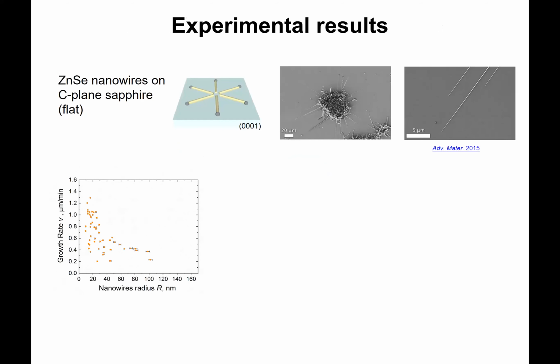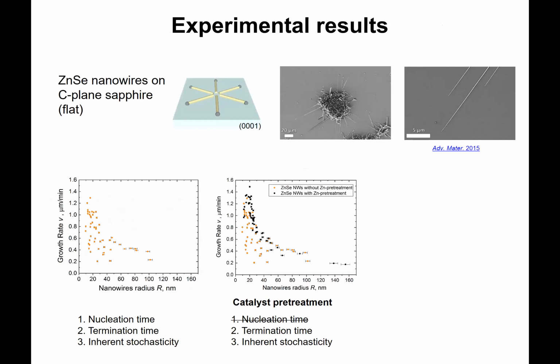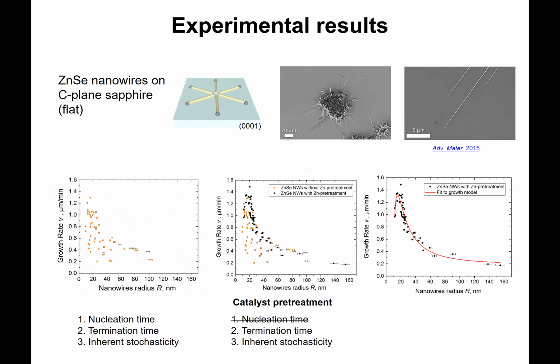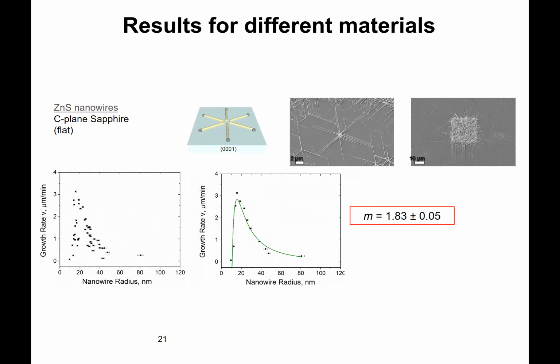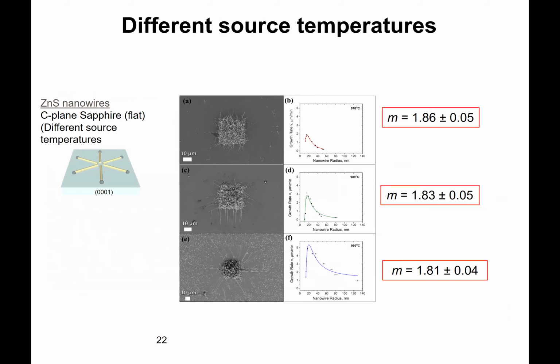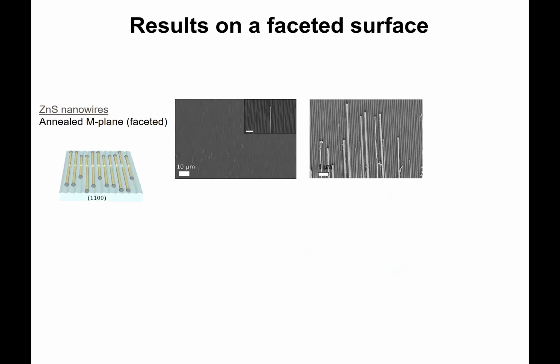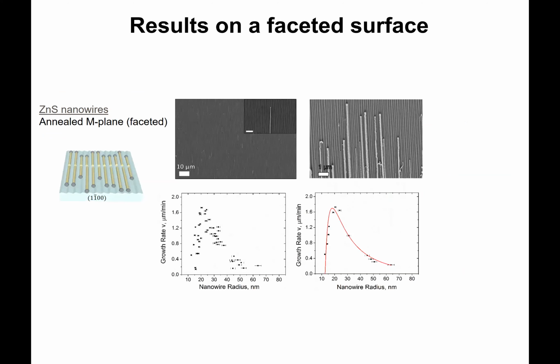And we did the experiments. I will not go into details because we're short of time. Okay, so basically we find that we have this dependence where the dimensionality of the surface diffusion is closer to 2 and not to 1.